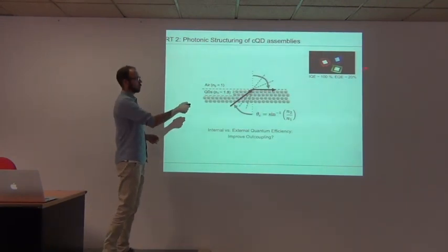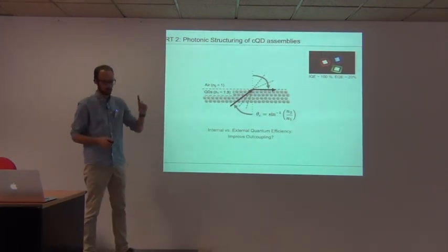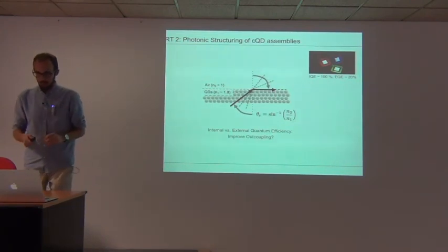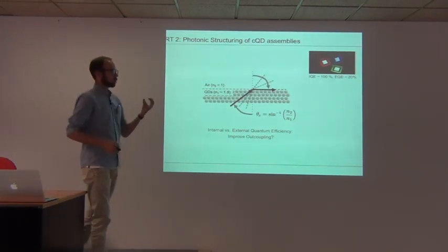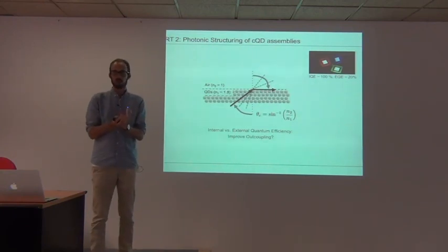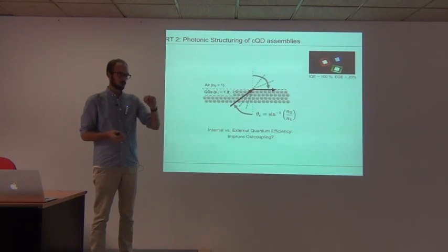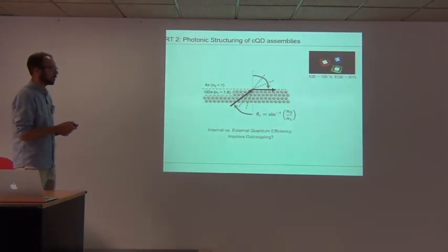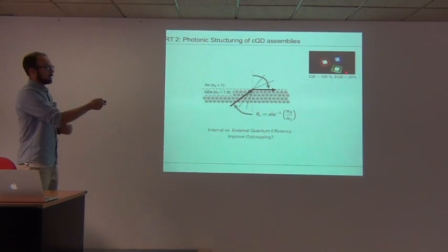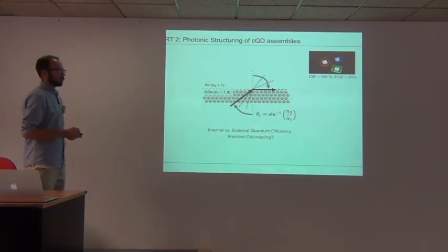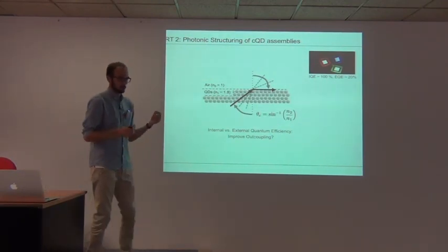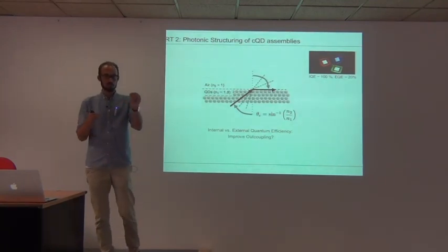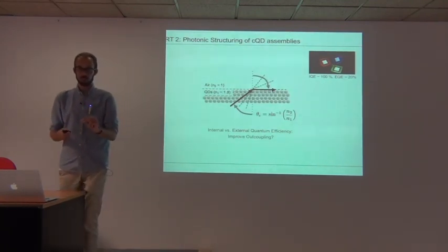So we have these TV screens, right? And people are also making LEDs out of these quantum dots. The interesting thing is that these quantum dots, thanks to all this passivation and everything, have quantum yields close to 1, meaning every photon that you use to excite them gives 1 photon out. This is really thanks to the advances in the synthesis. And actually, these LEDs that they are making have internal quantum efficiencies of close to 100%.